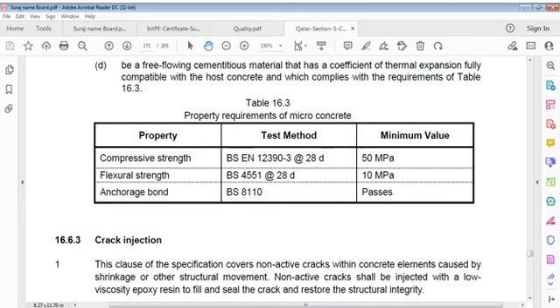Compressive strength is the property. Test method is BS EN 12390 and at 28 days it is 50 MPa. Compressive strength, that is the minimum value at 28 days. Flexural strength BS 4551, 28 day.